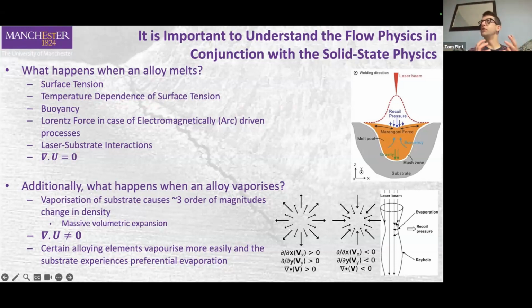It's really important because when you have these keyhole processes, these really high penetration joining processes that give you high throughput and increase your productivity, it's actually this vaporization that stabilizes what we call the keyhole or the thermocapillary. So you can see in this picture here, if you have a laser beam and we've got some sort of constriction starting in the keyhole, the laser beam will vaporize the portion that started to constrict. It will sort of bounce back, and that will stabilize that and allow us to have that high productivity.